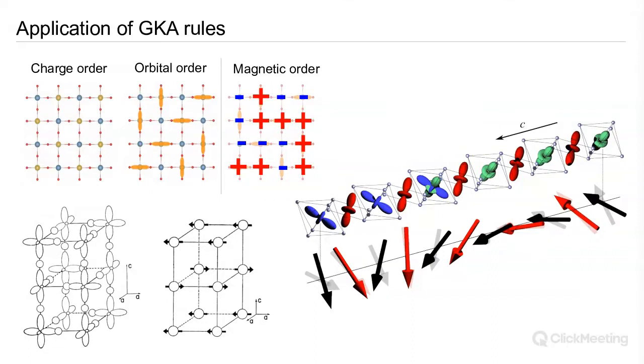In the case of this complex incommensurate phase modulated helix, we can actually apply similar rules, in that we can understand that as the orbital occupation modulates throughout the crystal, so does the nature of the exchange interaction that can then give rise to this phase modulation, where some regions of the magnetic structure are more ferromagnetic, if you like, and some regions of the magnetic structure are more antiferromagnetic as a result of this shift in orbital occupation.